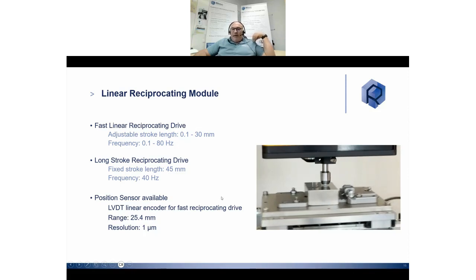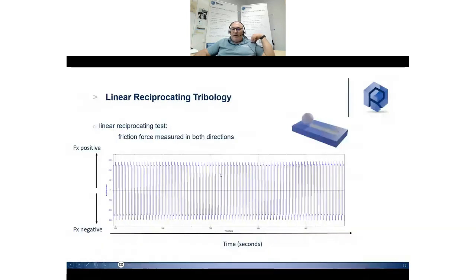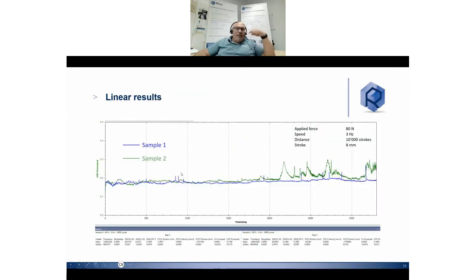And this one, again, if I show you a small application, if we are doing linear, we measure with linear reciprocating both directions, meaning the friction on positive and friction on negative. And it allows us to do naturally some curves, the displacement in function of the friction, but also here an example again on the same brake pads before. We use 80 Newton, pretty high load with a big ball, 3 hertz of frequency, 10'000 strokes with 8 millimeter, and we can differentiate different materials when it works in linear mode.